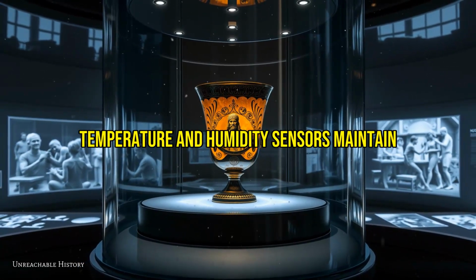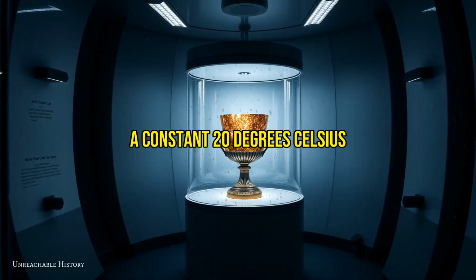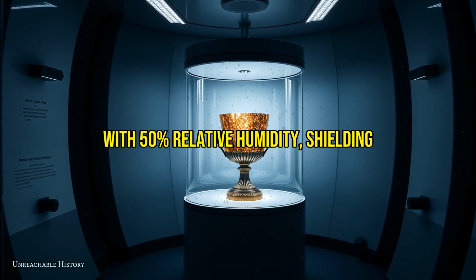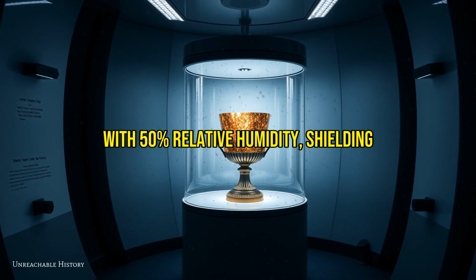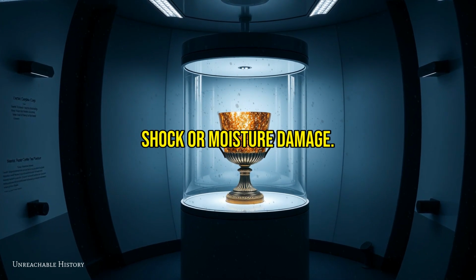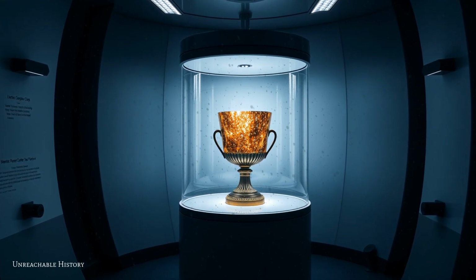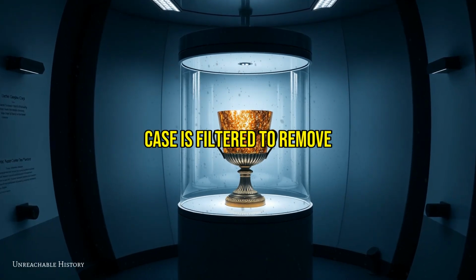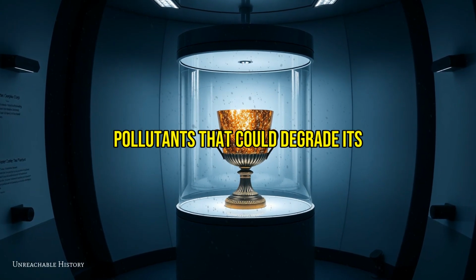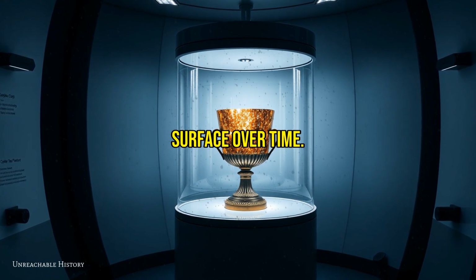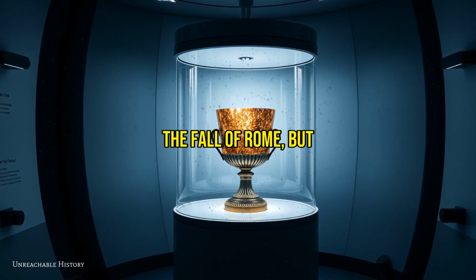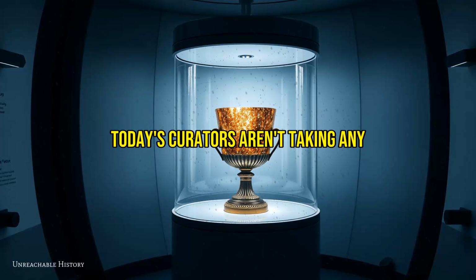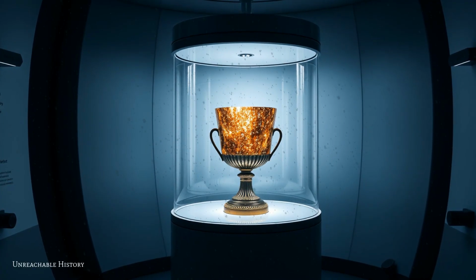Temperature and humidity sensors maintain a constant 20 degrees Celsius with 50% relative humidity, shielding the delicate glass from thermal shock or moisture damage. Even the air inside the case is filtered to remove pollutants that could degrade its surface over time. The cup may have survived the fall of Rome, but today's curators aren't taking any chances.